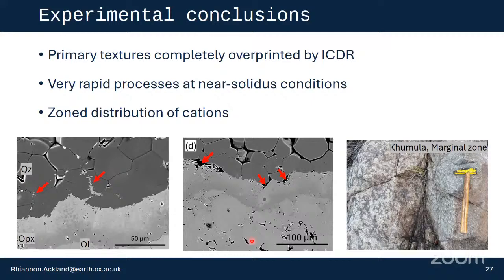So just to sum up what my preliminary experiments have found: primary magmatic textures can be completely overprinted by the replacive features. These are very rapid processes at near solidus conditions. In 2 weeks, I'm getting orthopyroxene rims that are already 40 micrometers thick. And so over the protracted cooling history of the Bushveld, this suggests that there's possibility for significant replacive textures of a large scale.